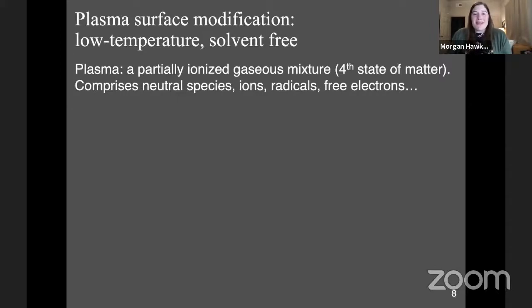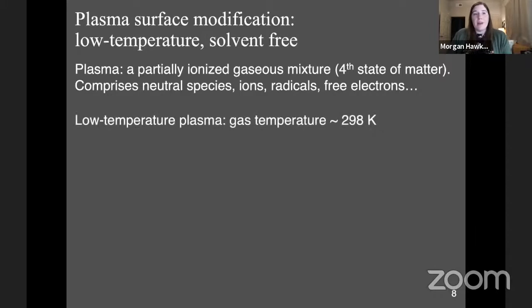So you might be wondering what's so great about plasma treatment. Well, first of all, the type of plasma modification that we do is effectively carried out at room temperature. What this means is that it can be used to modify many different types of substrates, including polymers that are somewhat delicate, without damaging their advantageous bulk properties that I talked about earlier. Also, because plasma treatment is a gas phase modification technique, it eliminates the use of any solvents. And this is especially key for polymer modification because many different types of polymers are incompatible with different solvent processing conditions used in alternative modification techniques like wet chemical modification.